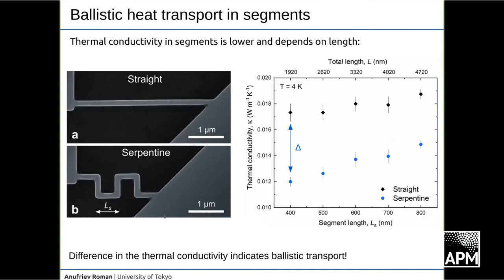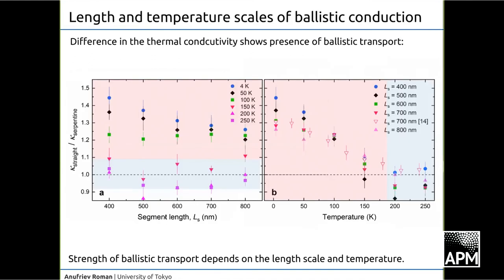This is what we did for different segment lengths and different temperatures, and we obtained an interesting plot. This plot shows the length and temperature scales of quasi-ballistic conduction in silicon nanowires, strictly speaking. Here we simply plot the ratio of the thermal conductivities of the straight nanowire to the serpentine nanowire, with one being the diffusive limit. With the blue I highlight the diffusive limit, and with the red, the ballistic limit.